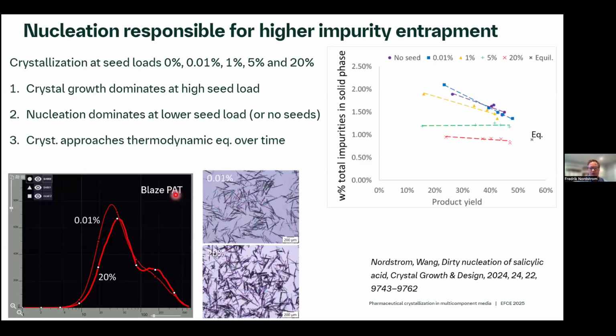But all right, so why do we see this behavior? Well, to answer this, we looked at crystallization at different seed loads. So we started by letting it crystallize by primary nucleation, and then we increased the seed load up to about 20%. And then we discounted the effect of those seeds to get corrected plots for what is actually crystallizing out over time. So that's listed here. Here again, you can see the 5 different seed loads. There's no seeds up here, and the 20% seed load is down here. And based on our phase diagrams and other experiments, we can calculate what equilibrium will actually be. And equilibrium in the solid phase will be close to 1%.